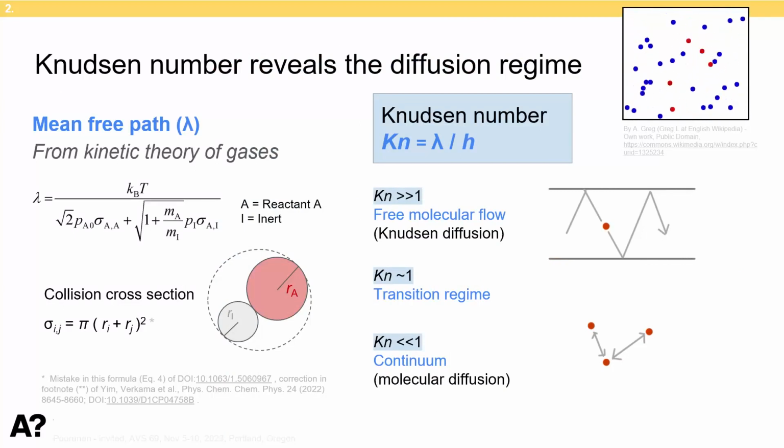So when we talk about conformal coating in a high aspect ratio feature, then you first need to transport somehow the molecules inside, and then they react. And depending on how the process parameters are, the growth might take place in various diffusion regimes. The most typical one is free molecular flow with Knudsen diffusion. So meaning that the gas is not very dense compared to the structure, the molecules are not hitting each other in the gas phase, but they are hitting the walls of the structure. Then you are in Knudsen diffusion regime.